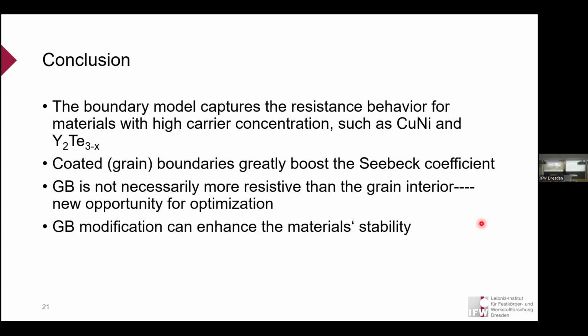And we could also use coating of these grain boundaries to boost the Seebeck coefficient. We also found that a grain boundary is not necessarily a resistive source, but it can also be much more conductive than the grain interior to promote the performance. And last but not least, grain boundary modification could enhance the material stability, to make this technology more practically relevant.